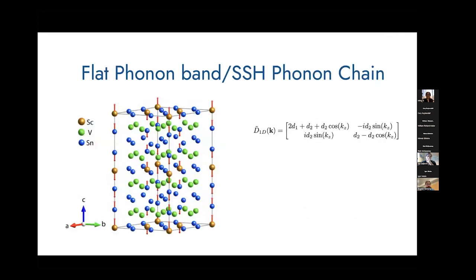So I'm going to gloss over a lot of details, but what we try to do is a combination. Obviously, we have the DFT and the first principles, but we try to get an understanding and a modeling that's a little bit beyond that, hopefully. So basically, we first try to get this phonon to see where it is localized. It's the phonon that goes soft in a second order way in the experiment, the one at the H point. And it's a phonon localized onto a trigonal tin. It's at momentum pi, and it's very flat in plane because of the way the trigonal tin couples to, for example, the kagome. And its model is basically, and you can theoretically justify this not only by ab initio but by just building a force constant model, seeing that